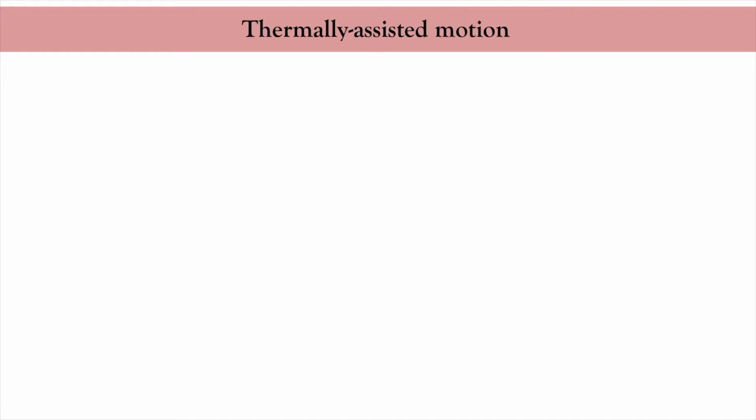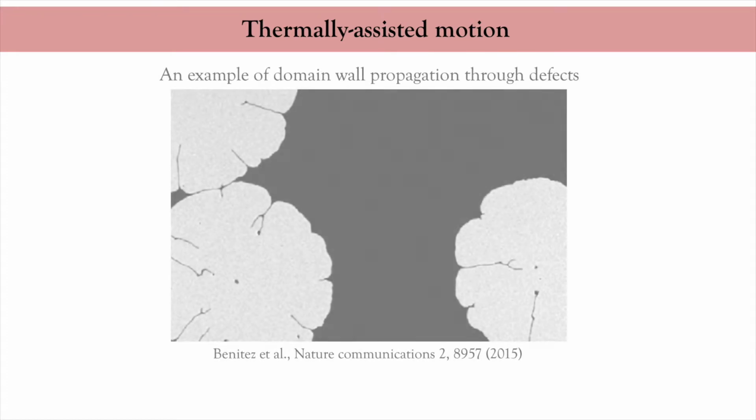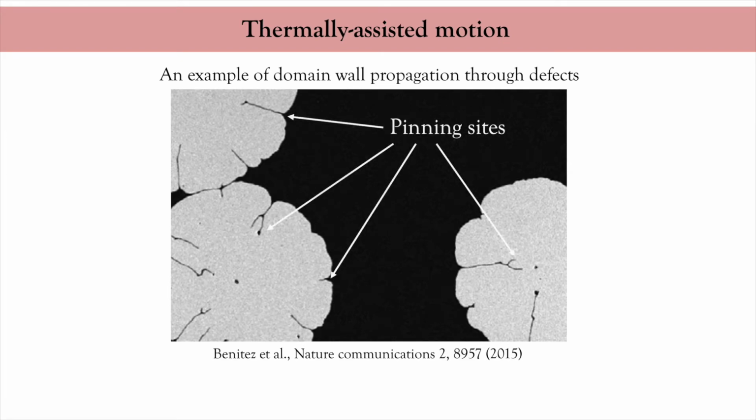The model for one-dimensional rigid domain wall motion works well in principle, but it is very difficult to find actual systems in which one can see the transition from the steady motion to the precessional motion. The reason is that magnetic defects are always present, and the pinning force coming out of those defects is usually much larger than the intrinsic pinning from Walker breakdown.